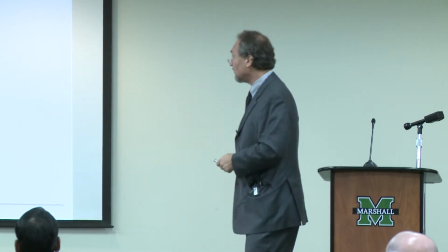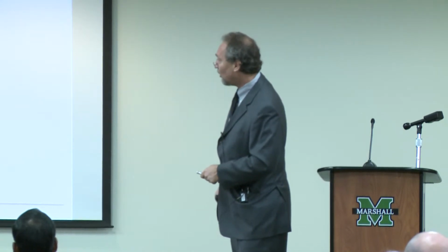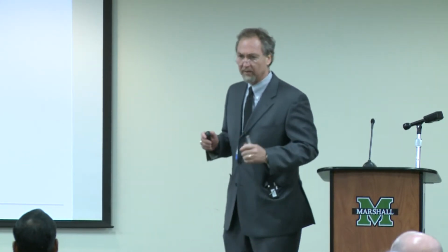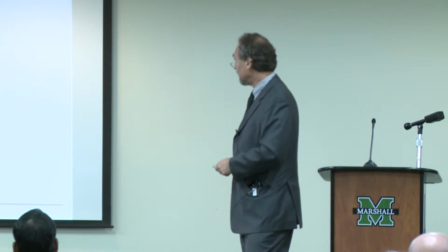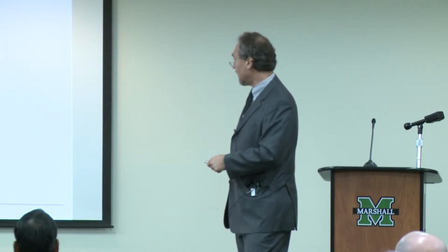Okay. However, if I want to go up to terahertz, I've got to change from niobium to niobium titanium nitride. Sounds easy, but now I've got to go out to Jet Propulsion Lab and have some people help me do that, because it's a very custom way of growing these films. The bolometer here is just aluminum covered with a little palladium. These are the contact pads.